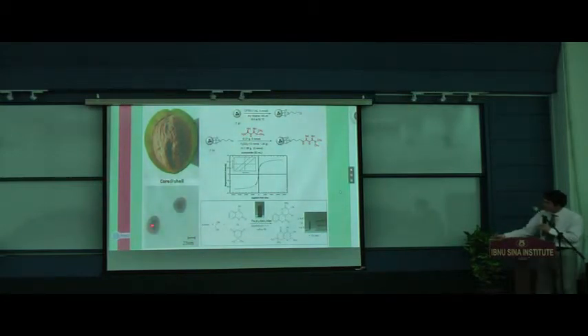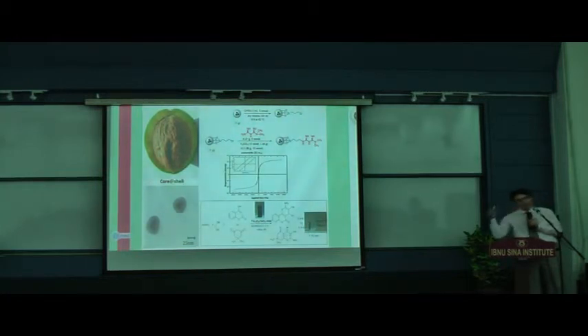As you see here, these are Fe3O4 magnetite, and this is the silica layer as a core-shell system. Of course, magnetism and simple catalytic application in organic chemistry reactions. And at the end, you can see easily, in less than 15 seconds, you can apply an external magnet, get your catalyst back, wash it and use it.